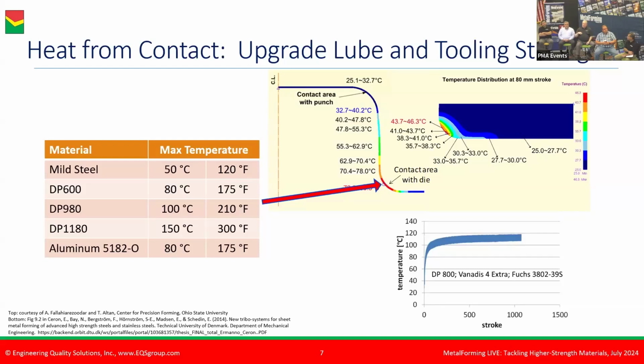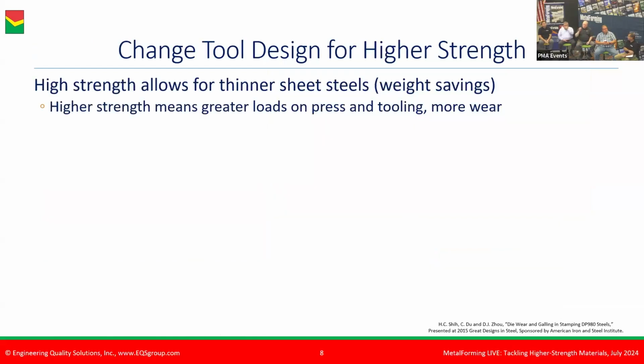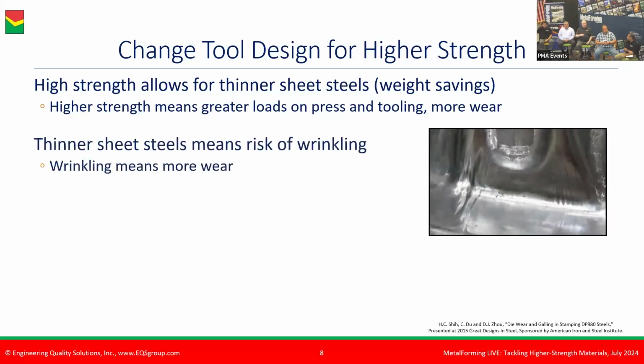If you are not using a lubricant that is designed to have the additives functional at those temperatures, you're going to run into problems with additional tooling wear. So we also need to keep that in mind and change our tool design approach as we're starting to work with higher strength materials, higher strength steels, aluminum, and stainless grades. Those higher strengths will allow for a thickness reduction, which is great because that could lead to potential savings. But that higher strength means increased press loads and potentially increased tooling wear.